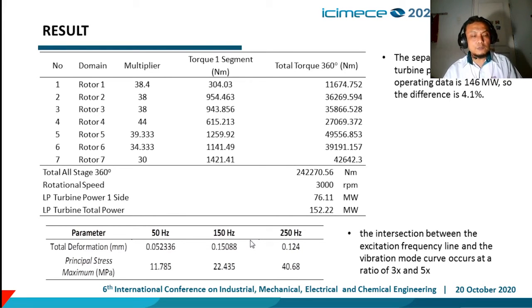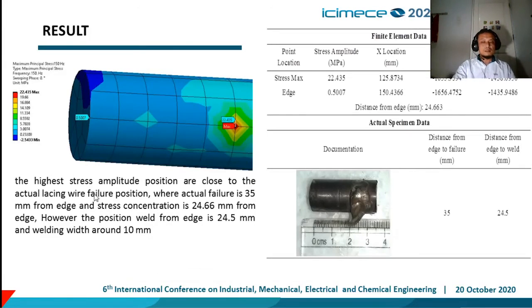The stress evaluation is plotted using the operating frequency of 50, the first natural frequency and the second natural frequency. The intersection between the excitation frequency line and the vibration mode curve occurs at the ratio of 3 times and 5 times. The position of the higher stress amplitude is close to the actual lacing wire failure position, where the actual failure is 35 mm from the edge and the stress concentration is at 24.66 mm from the edge.